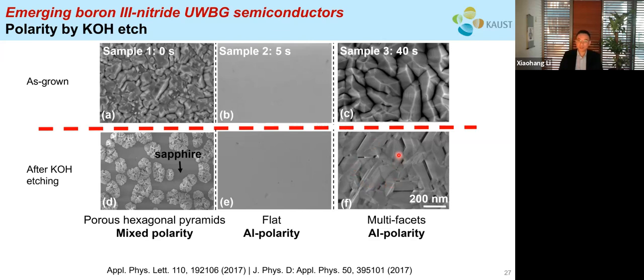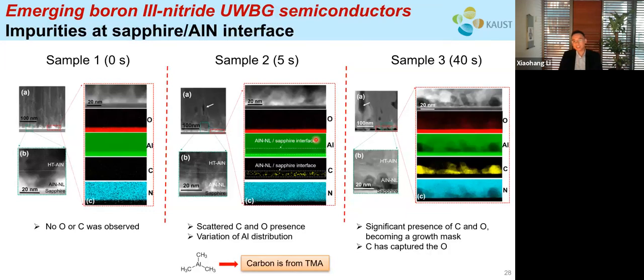The reason that those facets were gone is because the KOH can attack and etch away those facets very well, but cannot etch away the so-called C-plane aluminum nitride, which is the flat surface. So to further investigate this, we conducted a TEM study with the emphasis of looking at the impurities between aluminum nitride and sapphire. The impurities can include carbon. And where is the carbon from? The carbon is from the trimethyl aluminum, which is the precursor for the pre-treatment.